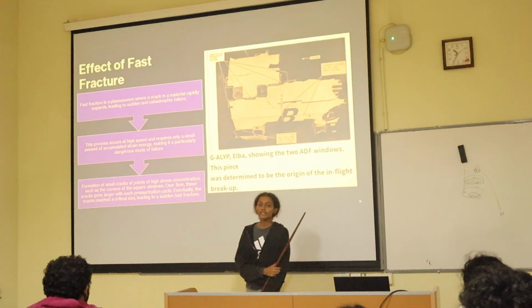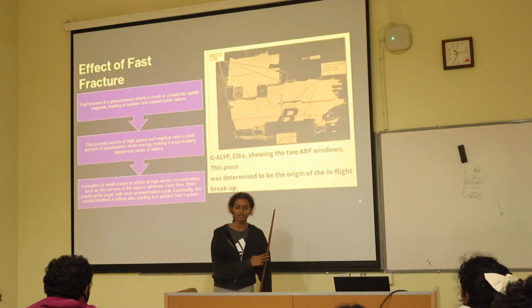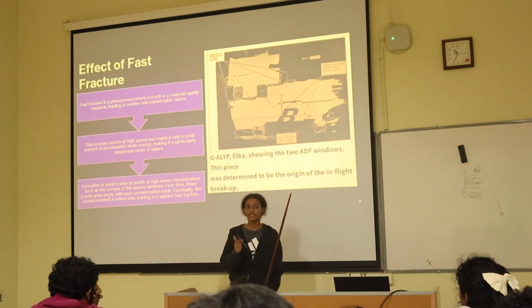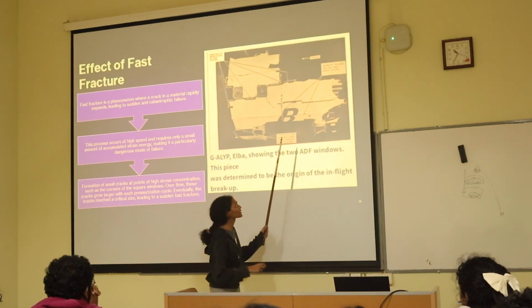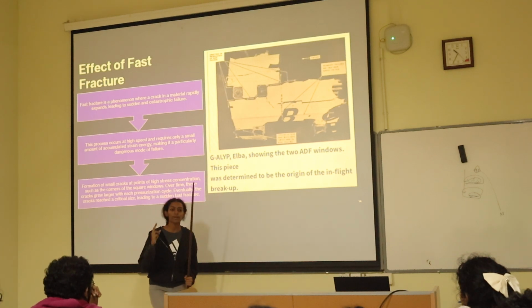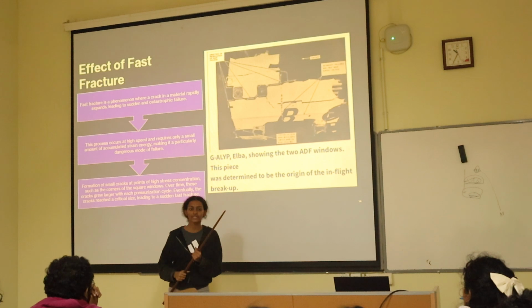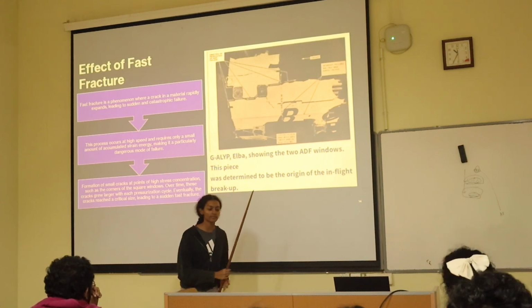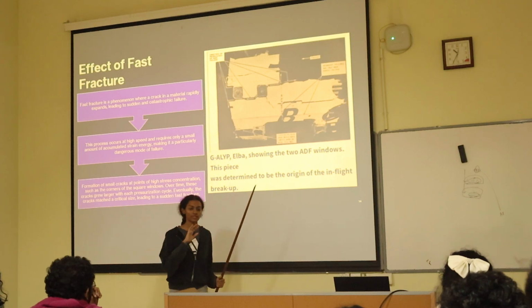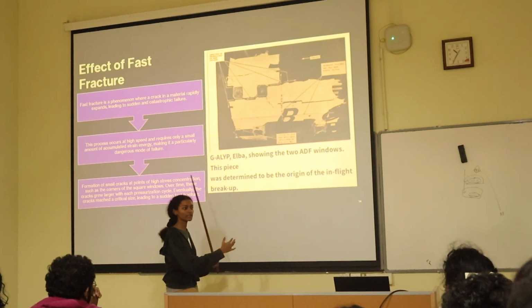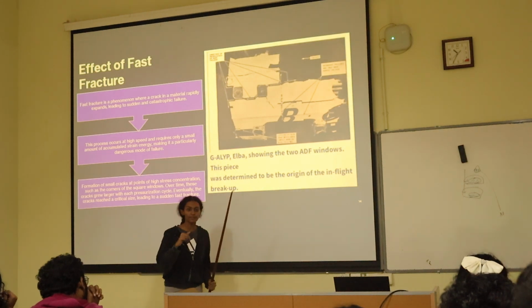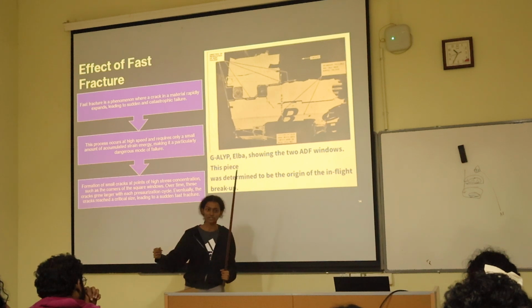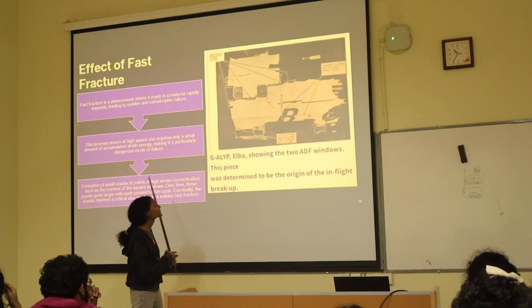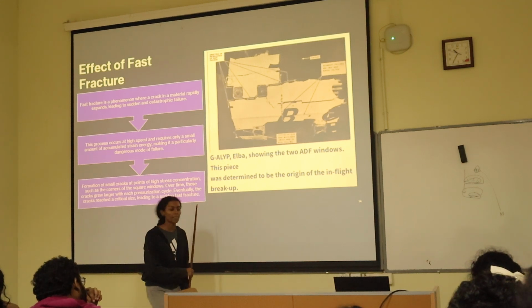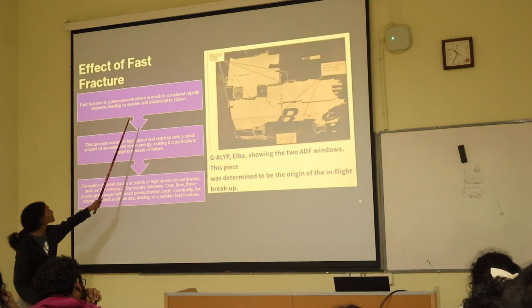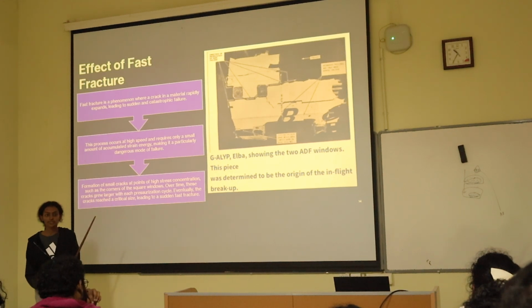So we can see that there are 3 main reasons why this fails. One, high stress concentration around the corners of the square windows. Two, punch riveting. Punch riveting is used to bring two surfaces of the aircraft together, but when we give a lot more load, this created micro cracks around it. So these were points of fatigue propagation. And three was fast fracture.